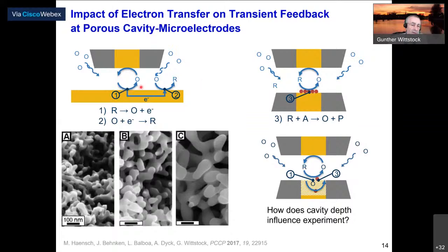I would like to explain this feedback effect, which is also very important here. This is when we have a microelectrode and the substrate is a large electrode, and we try to make such a titration experiment. We would titrate this here, but without applying external potential, we would still get an electron transfer to a region which is far away. And since our solution contains initially only the oxidized form, we form a concentration cell which can drive the back reaction here without titrating the adsorbate. So in that situation, we could not make a titration. We can only make that if the size of that electrode is restricted to that size. On the other hand, such effects, where the concentration cell drives a conversion, can also be exploited, and we will see in a moment that this is also the case here for the cavity microelectrodes, but in a slightly different way.